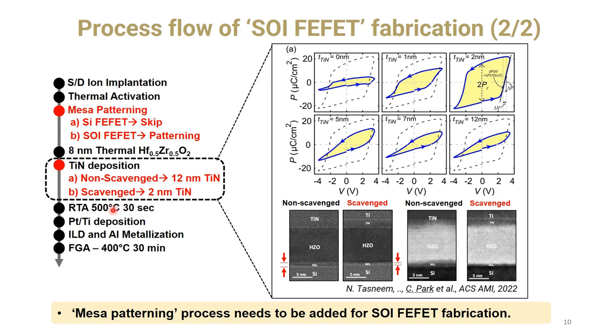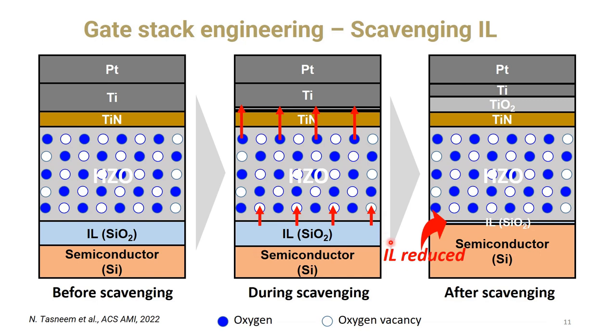And then we annealed the fabricated layer at 500C, and then Pt/Ti deposition as a gate metal layer, and ILD passivation and aluminum metallization. We also did the FGA process. And here is the mechanism figure of the scavenging of the IL.